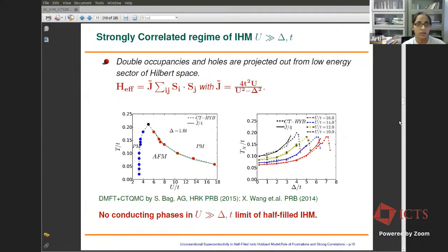So if you do some kind of Schrieffer-Wolff transformation on this half-filled ionic Hubbard model in this limit, where Hubbard U is the largest energy scale, you will see that it maps onto an effective Heisenberg model. And the only difference compared to the case of the half-filled Hubbard model is that now the spin exchange interaction has a non-monotonic dependence on the staggered potential. So one can actually tune the Néel order by tuning the ratio of U by delta. And this is what we saw in one of our earlier works, that the Néel temperature can be enhanced by bringing delta close to U within the limits of this calculation.